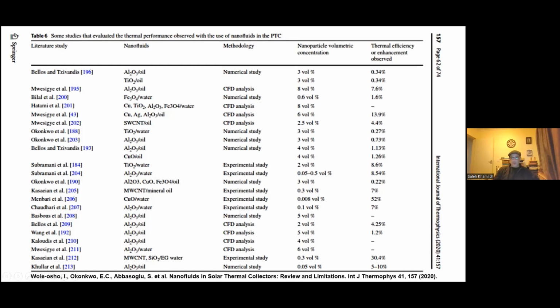But the most beautiful one here, look with me down there, is this Kassasian, a scientist who managed to use what we call multi-walled carbon nanotubes and also silica in ethylene glycol in a parabolic trough solar collector. They managed to achieve 30.4%. This is really very good because by using a nanofluid based on that, this scientist managed to prove that the enhancement of a parabolic trough goes up to 30.4%. This means that nanofluids will really contribute to enhancing the performance of parabolic trough solar collectors.